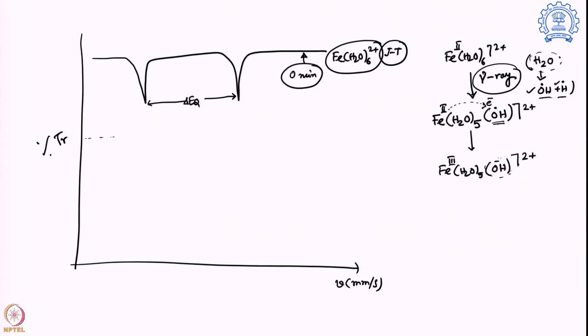So over here we continue to see these bands as it is, so that means it is actually staying there. But additionally, we started seeing another set of peaks appearing, which has a little bit lower delta EQ value. And not only that, the delta value for this new one is actually a little bit on the negative side compared to the delta value of the original iron 2 plus system.